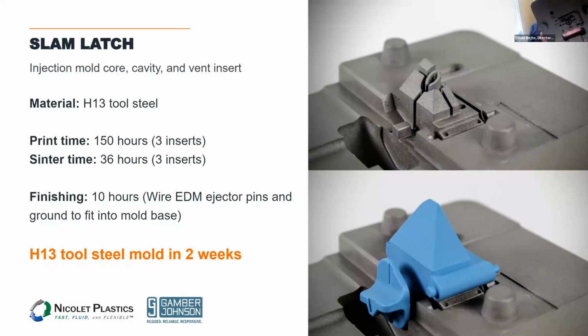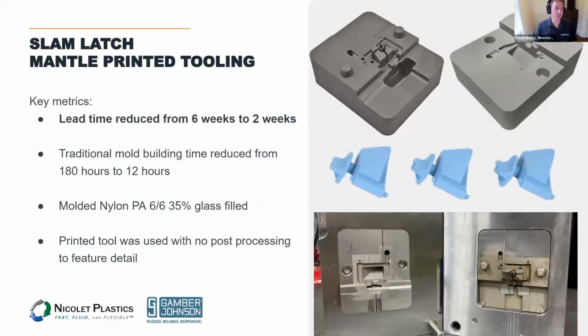If you can see some of these features on top here, very deep ribbed features that would have required pretty extensive EDM to produce, which really made it a great fit for Mantle, because Mantle was just able to simply print those features right into the part. Some of the key metrics here: reduction of lead time from 6 weeks down to just 2 weeks. If they were building that tool themselves, because of all the EDM work required, they're estimating 6 weeks, down to just 2 weeks, because it only required 12 hours of their toolmaker's time compared to 180 hours of what they estimated traditionally.